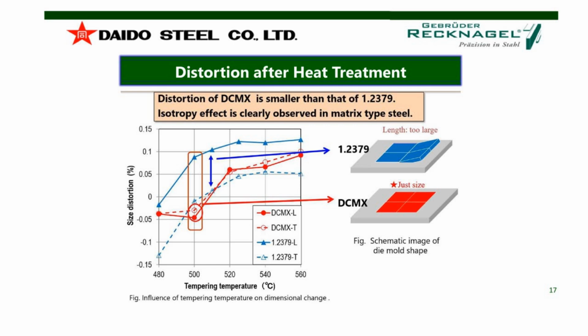And the situation with DCMX is absolutely different. You can see both points for length and thickness distortion are on the same level. If you use a temperature of about 500 degrees, or more commonly about 520 to 540, you have always a very isotropic distortion of DCMX. And that means if you produce, for example, a cutting plate, or a segmented punch, where you need a very small distortion, your product will fit much better than with D2 grade. That's the point of this chart. Yeah, let's go forward.